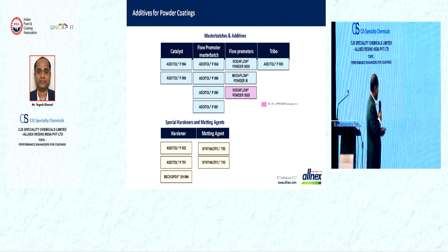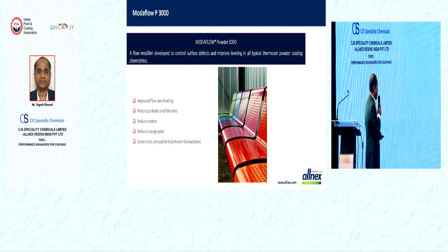Then recently in our portfolio, we have launched this MODAFLOW Powder 3000. It is a flow modifier developed to control surface defects and improve leveling in all typical thermoset powder coatings. It improves flow and leveling, reduces pinholes and fisheyes, reduces craters, reduces orange peel, and has good cross compatibility between formulations.